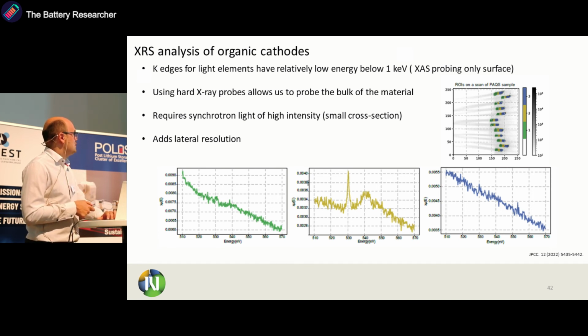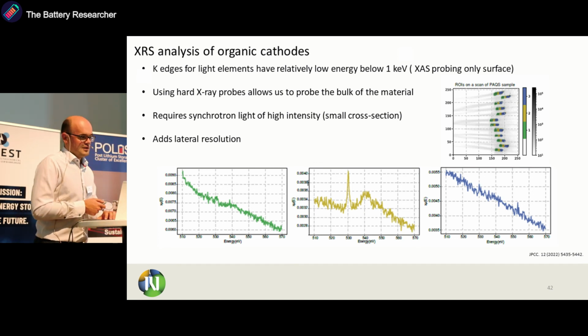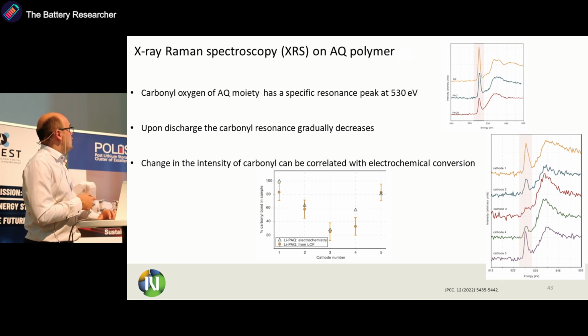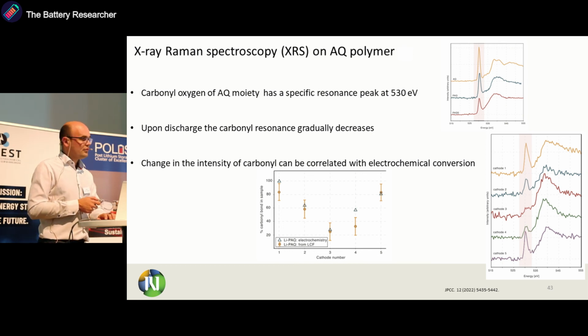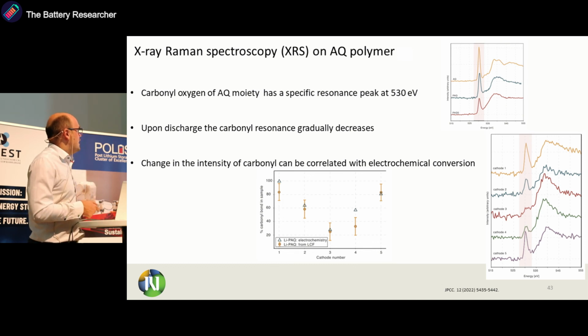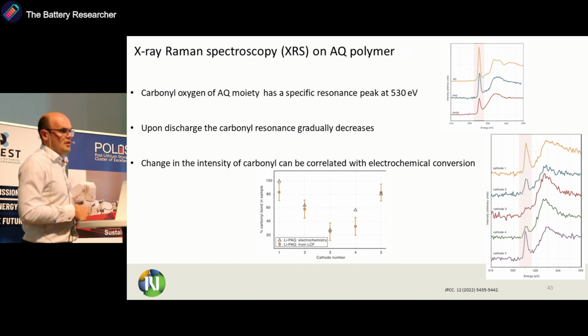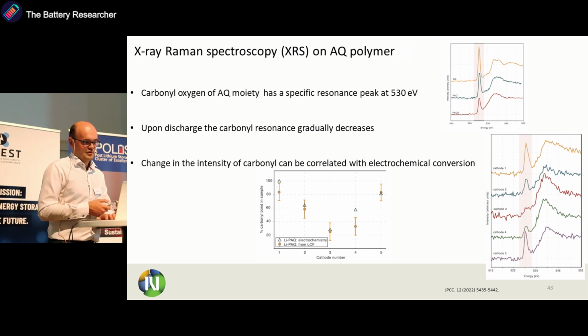So basically here we have 3 areas which are picked, and this is like with the window before, this is our electrode, and this is then the backside. And you can see that this oxygen spectra is just present inside the electrode. And we did this on anthraquinone polymers because carbonyl oxygen of AQ moiety has a specific resonance at 530 eV here. And you can see it's present in anthraquinone and also in both polymers, polyanthraquinone and polyanthraquinone sulfide. And when you do discharge and charge back, you can see that in discharge this decreases and then increases again. And you can quite nicely correlate this intensity with the electrochemical conversion that you get from the electrochemistry.